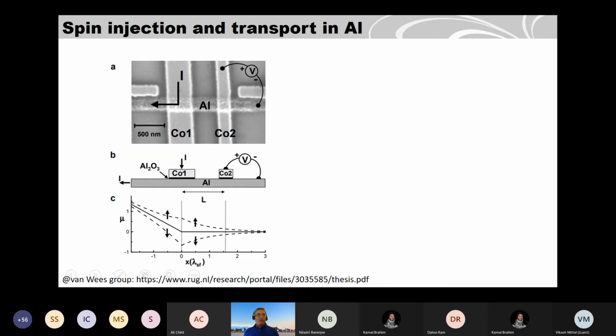Then, because it's a non-local measurement, current is going here and spins are diffusing in this channel. So you have this splitting of the electrochemical potential. They will decay with distance because it's not a magnetic material, it's a non-magnetic material. The non-equilibrium spin you created will decay in this material.